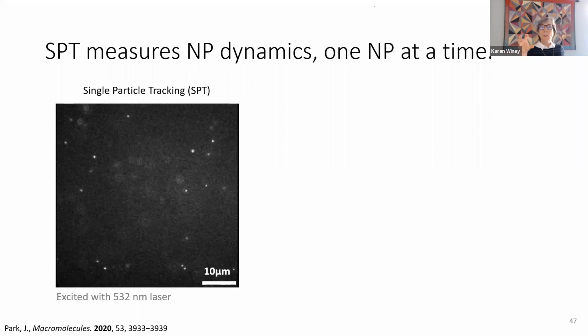One of the things that's difficult about doing that nanoparticle diffusion experiment is if the particles are athermal, and you have to do a very long anneal, they will agglomerate. Because to have enough signal, we have to put in like at least 5 or 8% particles. So we've gone to single particle tracking.